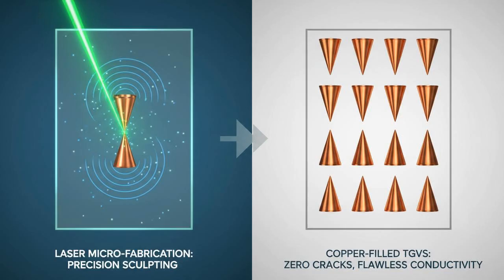First, an ultra-short pulse laser is fired at the glass, but it doesn't burn a hole. Instead, it changes the molecular structure of the glass in a tiny column, making that specific spot more soluble. Then, the glass panel is dipped into an acid etching bath. The chemical eats away the laser-modified glass 50 times faster than the rest of the panel. The result is perfectly smooth, tapered holes created instantly across the entire panel, thousands per second, with 0 microcracks.